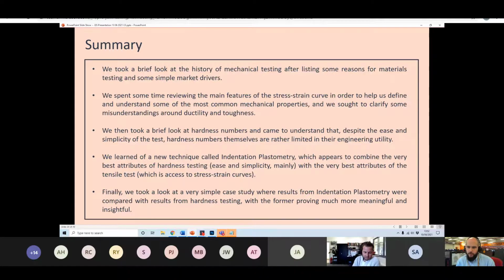Next one we've got coming in is what is the minimum recommended material sample size for plastometry testing? Great question. It depends on the size of the indenter that you're using. So when we supply our machines, we send 2 indenters. One's got a 2mm diameter and one's got a 1mm diameter. As I've said before, that's quite large relative to nano indentation testing or even Vickers indentation testing. And that dictates what the minimum sample sizes are. So if you're using the 2mm diameter ball bearing, then we say the minimum sample dimensions laterally are 5mm by 5mm. The reason being is we don't want people to be indenting too close to a free edge. And if you indent too close to a free edge, that can distort the shape of the profile, the shape of the indent, and therefore it undermines the modelling assumptions that are taking place in the background.